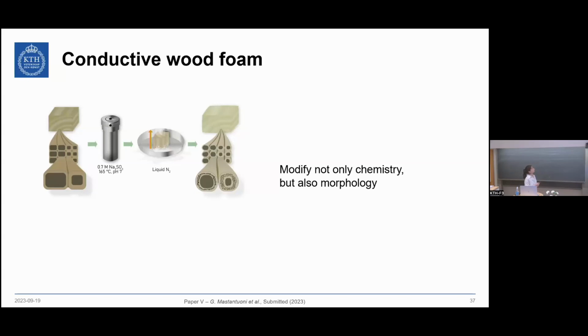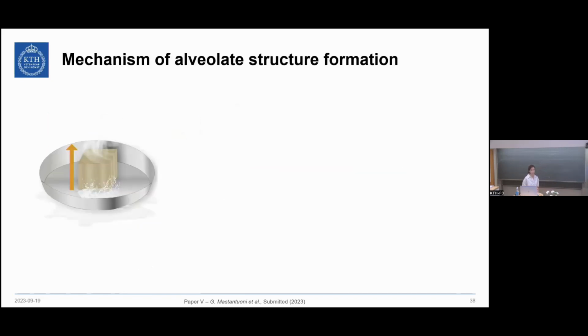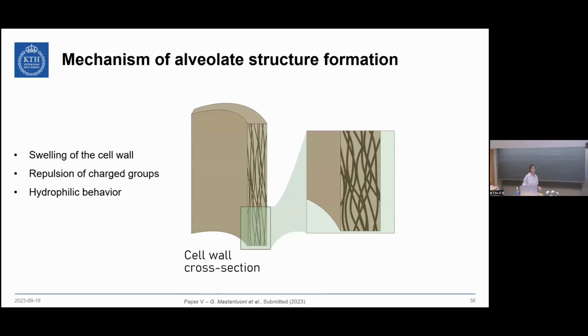So in this case, the sulfonation was followed by directional freezing to achieve what we call wood foam, with a much enhanced porosity in the wood cell wall. This was followed by the infiltration of the exact same pre-polymerized PSS as the previous study. So first of all, what happens during freeze drying? We put the samples with the fiber direction vertical on top of liquid nitrogen. Then we take advantage of what happens during sulfonation, which means that we're swelling the cell wall because of the repulsion of the sulfonic groups within the material. At the same time, the hydrophilic behavior also increases and we have more charged groups inside the structure.